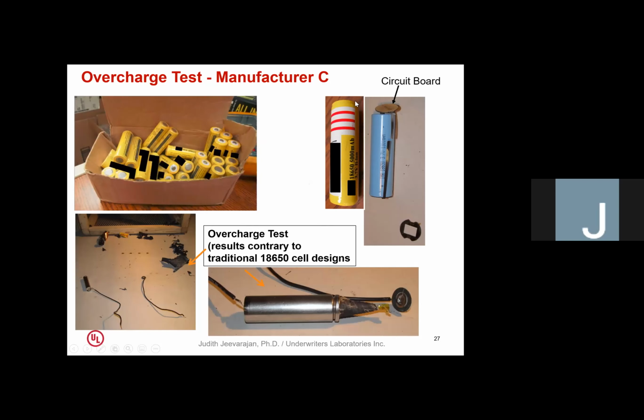And we opened up the can and found that there was another cell inside the can with the circuit board attached to it. And the cell said that it was about 1300 milliamp hours. And when we tested the cell, we got only 600 milliamp hour capacity from the cell. And we did an overcharge test, and this circuit board actually prevents the cell from going into thermal runaway.